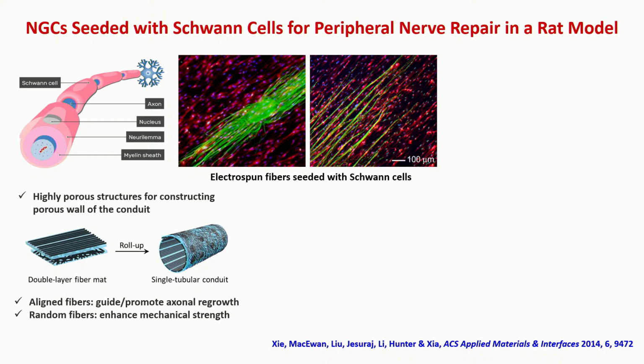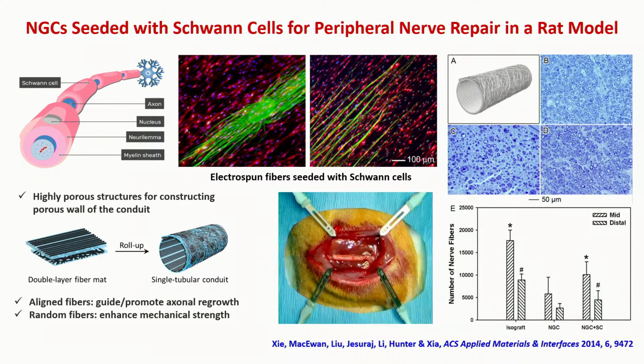So that's why we put these aligned fibers on top of these random fibers, and then you roll up and seal them at the edge, and that's basically going to be the conduit. This conduit has porous walls that come from the natural deposition of the fibers. And on the inner surface, you're going to have these uniquely aligned physical structures that can provide for axonal regrowth. So we did this with a rat model for sciatic nerve repair.